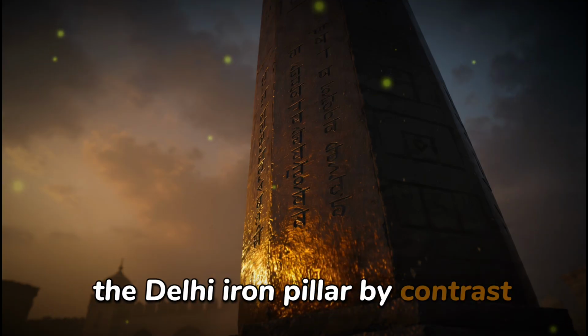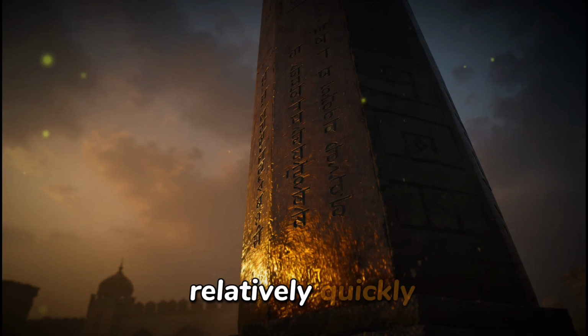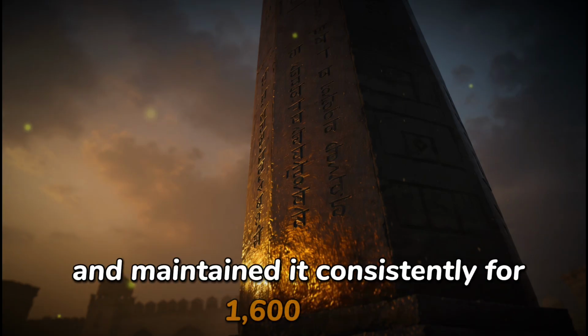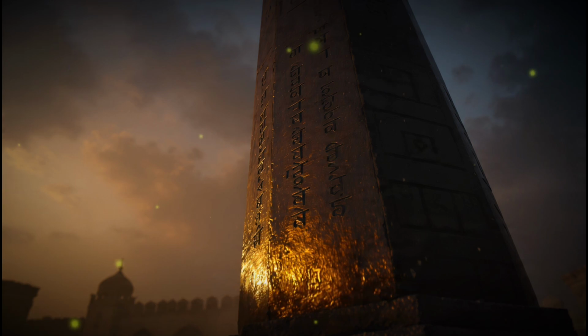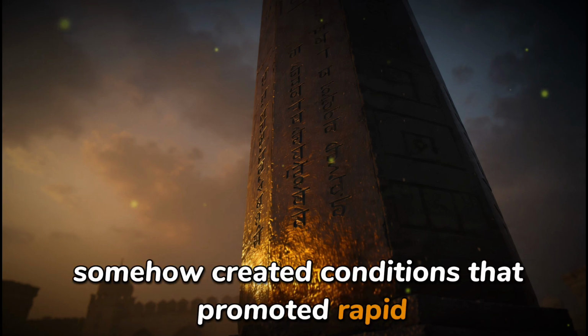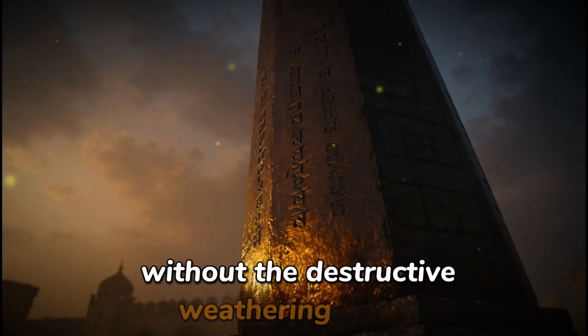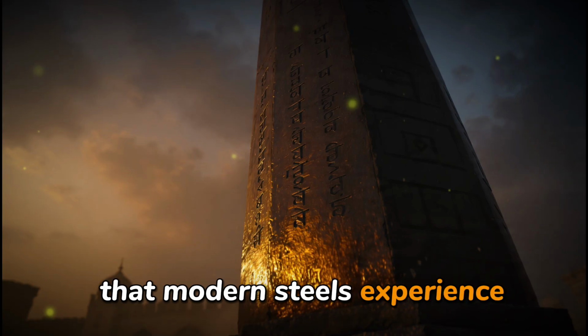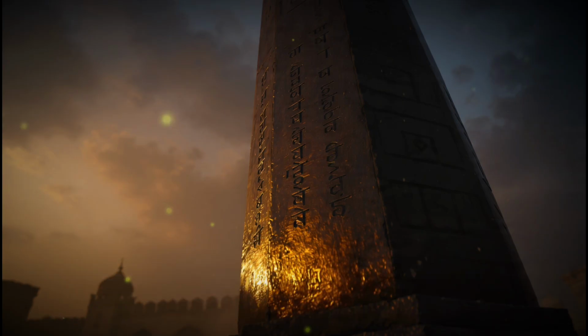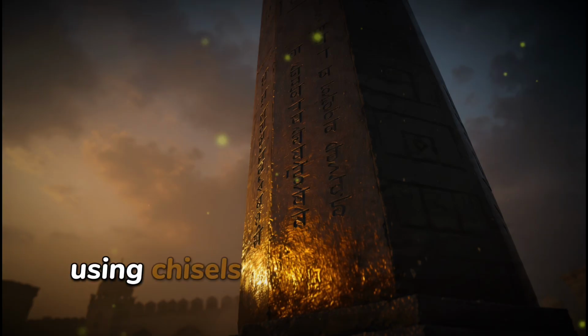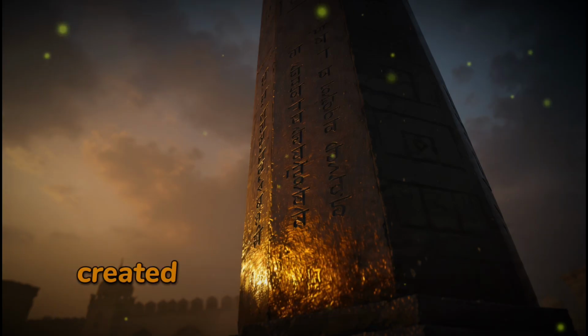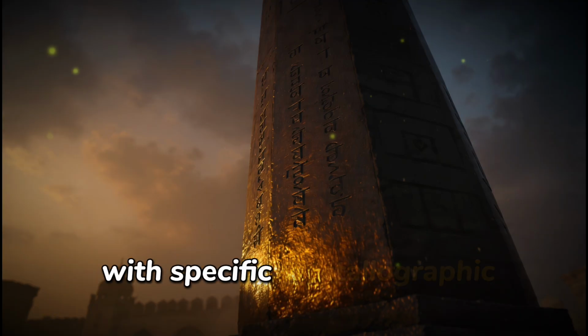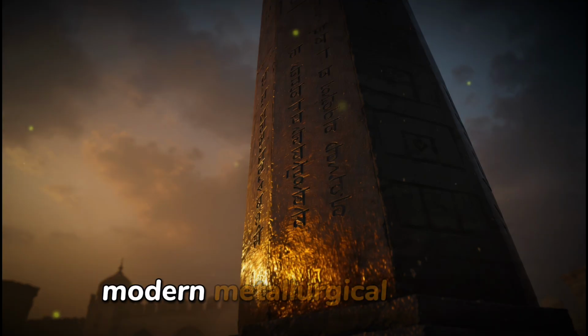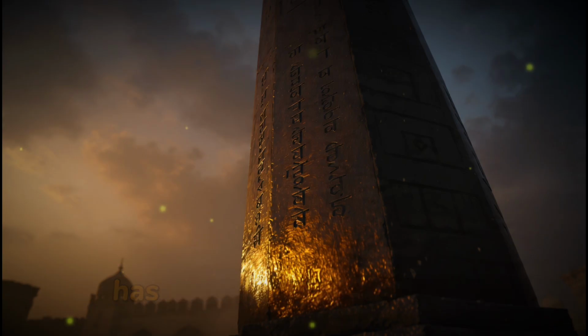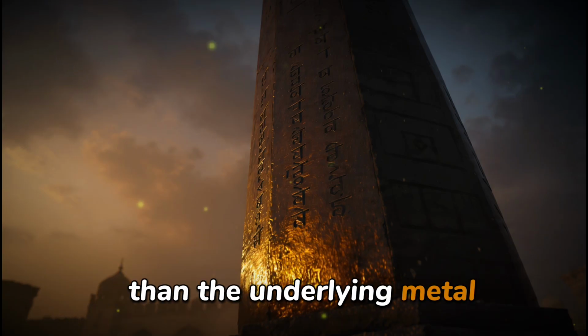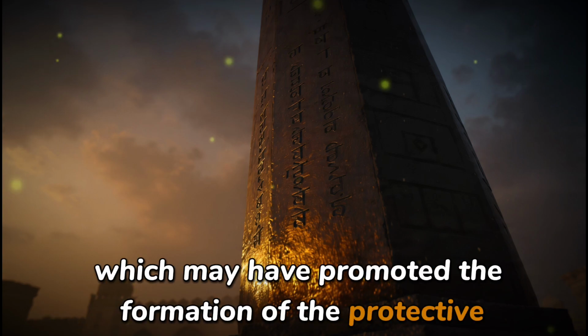The Delhi iron pillar, by contrast, seems to have developed its protective layer relatively quickly and maintained it consistently for 1,600 years. The ancient smiths somehow created conditions that promoted rapid protective film formation without the destructive weathering period that modern steels experience. Part of this may relate to the surface preparation. Ancient finishing techniques, using chisels and burnishing tools on hot metal, created a work-hardened surface layer with specific crystallographic properties. Modern metallurgical analysis has shown that this surface layer has a different grain structure than the underlying metal, which may have promoted the formation of the protective phosphate film.